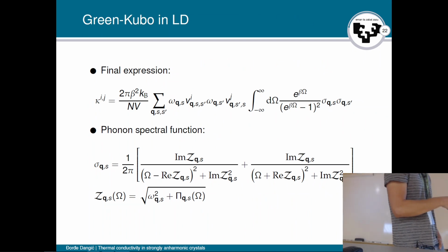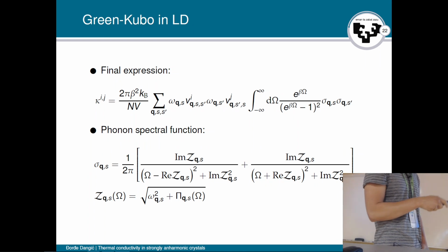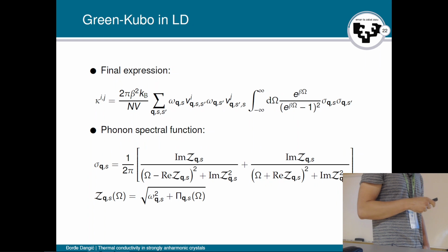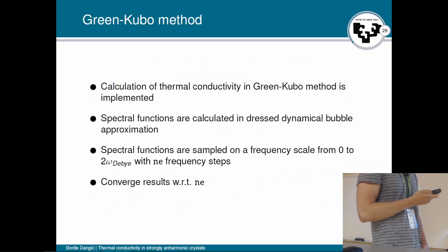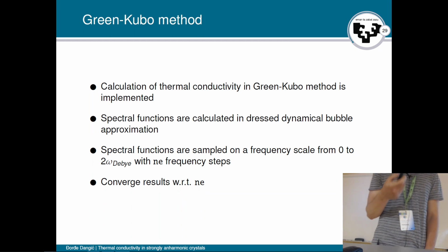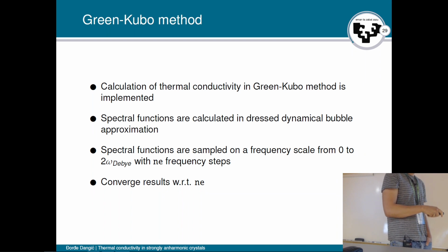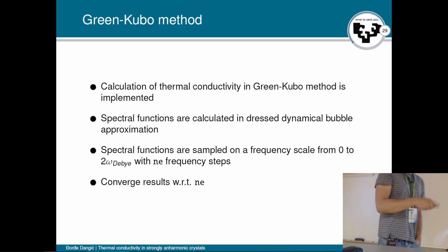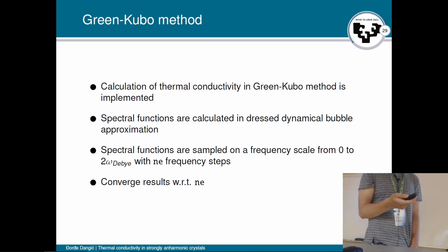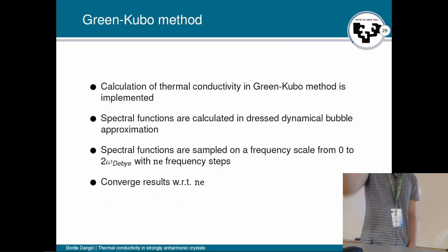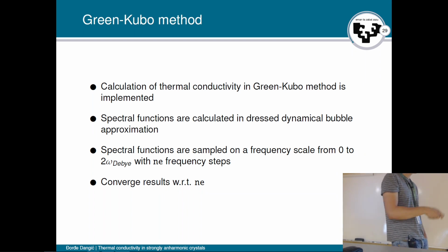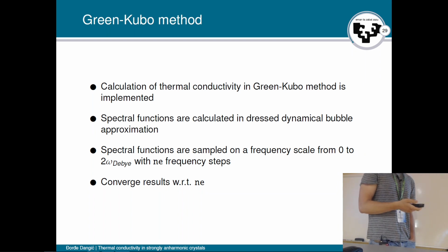So we take this range of frequencies from -2 omega_D to 2 omega_D, where omega_D is used because that's where you can have the ghost showing up in the phonon spectral function. We use a number N_E of frequency steps, and then you have to converge with respect to the number of these frequency steps. The problem here is that the step between neighboring frequency steps in the integration of the spectral function has to be smaller than, or at least comparable to, the lowest phonon linewidth. Otherwise, if it's too big, you're just going to skip your phonon spectral function altogether. So it has to be sufficiently small to actually see the whole phonon spectral functions.